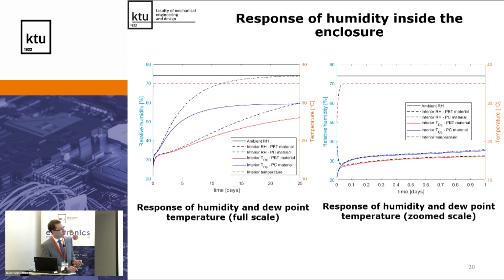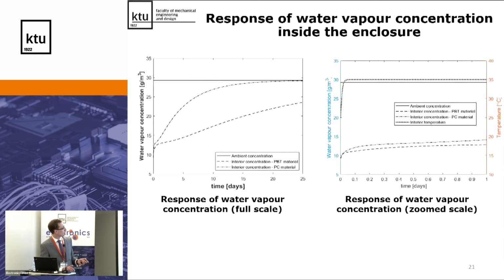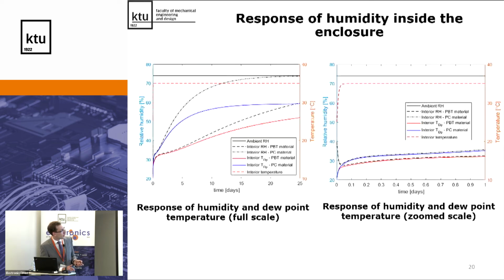And here the blue and red lines represent the dew point temperature. Dew point temperature is defined by the amount of moisture in the air, and it represents the temperature at which we can get condensation. As you see, it starts increasing from the beginning, because the concentration of moisture is increasing inside the box. And here I would like to show the concentration profile. If I go a bit back, I forgot to mention that in the beginning, when we have a non-isothermal case, we have sudden changes.